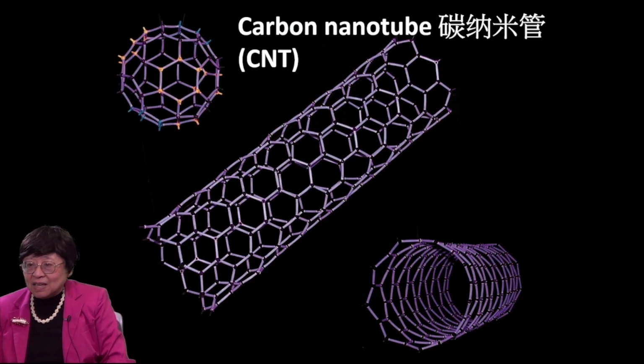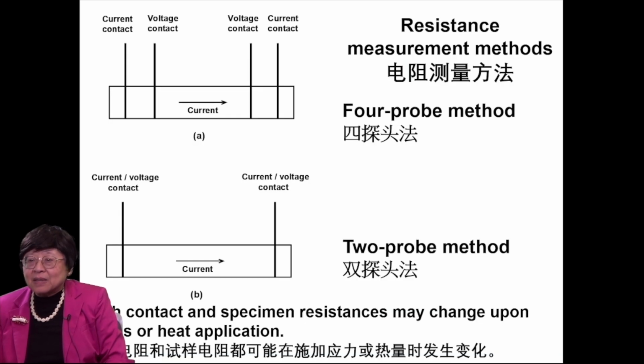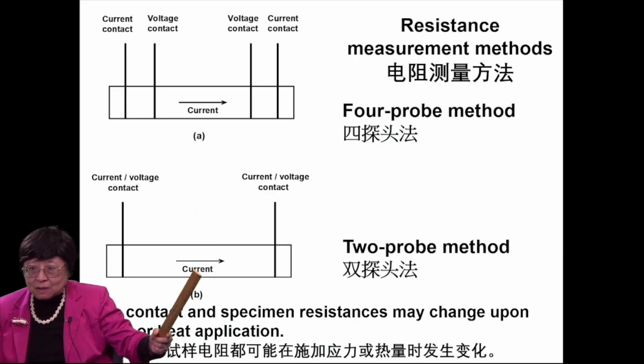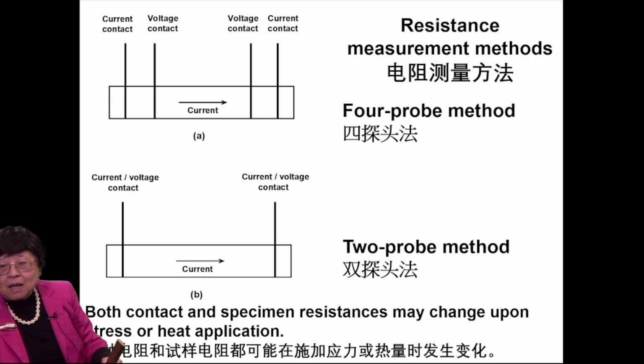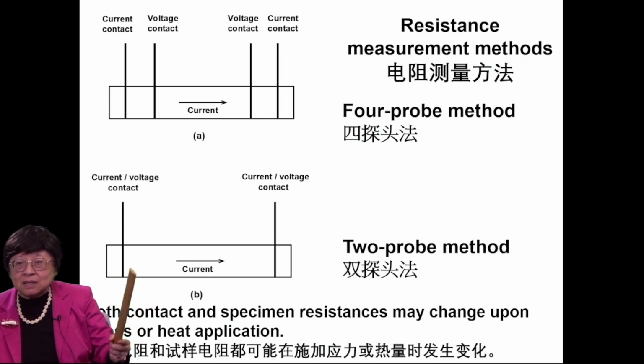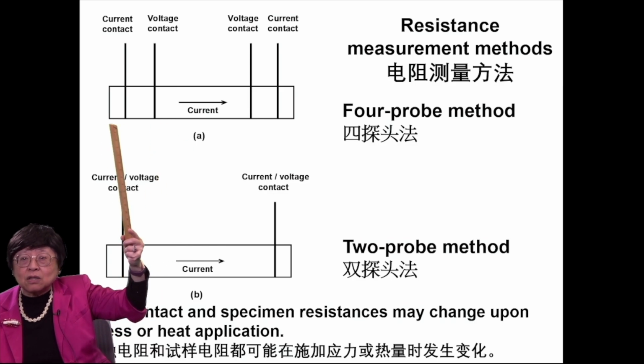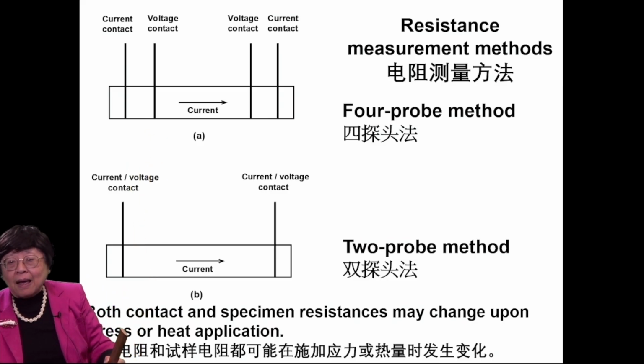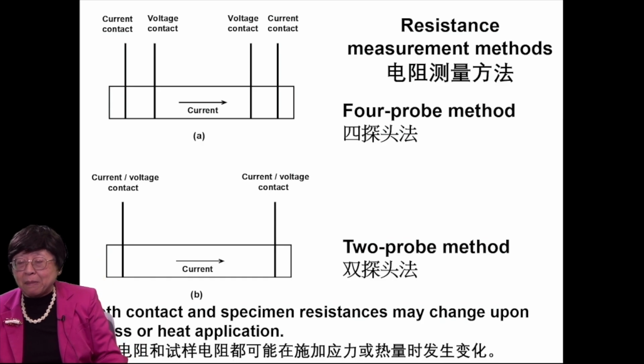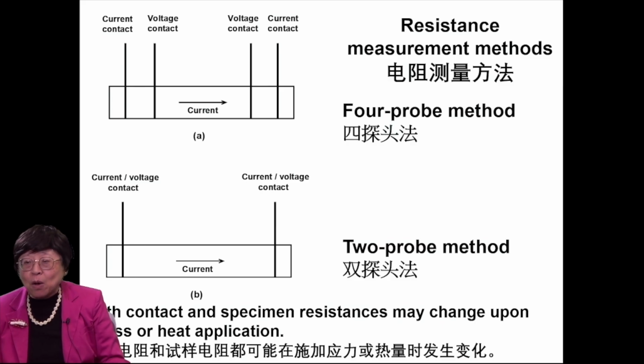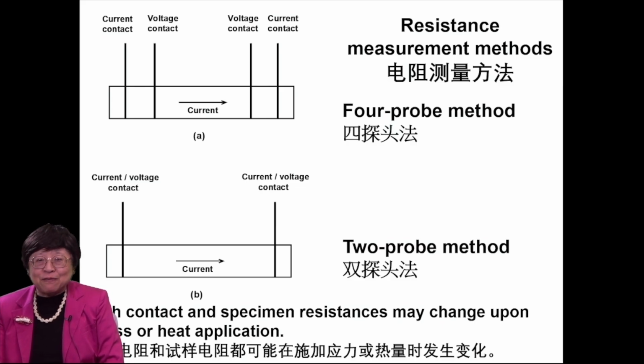Carbon nanotube, or CNT, has received a lot of attention. And I should mention, first of all, that the 4-probe method versus 2-probe method are very different. The 2-probe method includes the contact resistance of the two contacts in the measured resistance, whereas the 4-probe method essentially excludes the contact resistance from the measured resistance. And both the contact and specimen resistances may change upon stress or heat application. So if you use the 2-probe method, you have not just the specimen changing, you have the contact quality changing. So both things changing. So it's hard to find out what's going on.